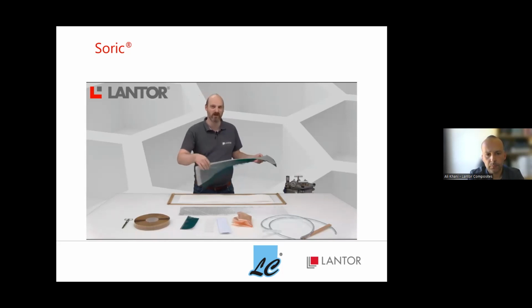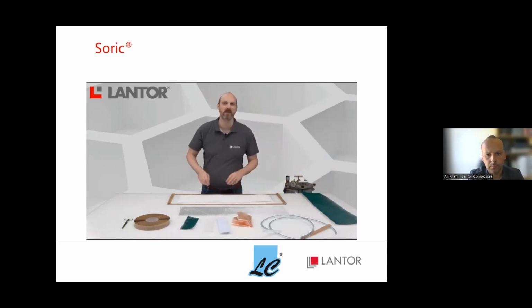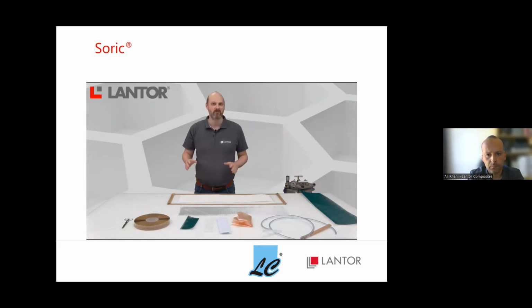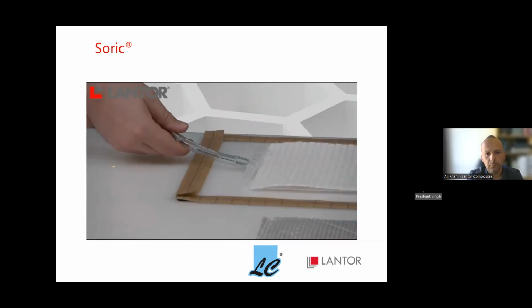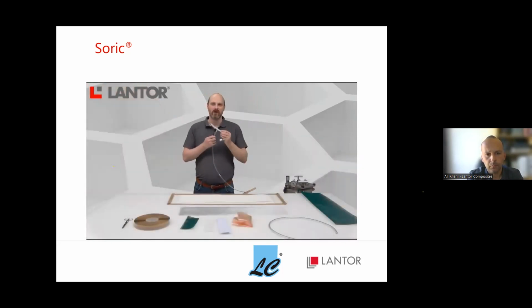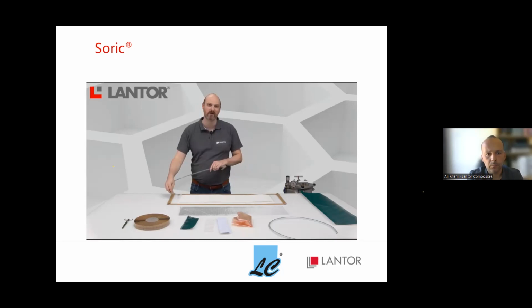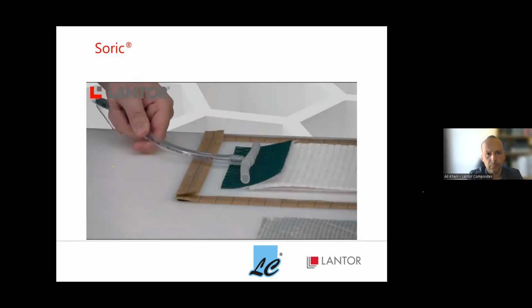We will not be using these large pieces, which will become waste, because it will be the Soric that is going to facilitate the resin flow. And unlike the flow mesh, Soric is part of the final product. That means that our resin feed line comes here. We stretch out the spiral hose so it stays open. And we position the spiral hose to make contact with the Soric to assure an optimal resin flow, aided by a small piece of peel ply and flow mesh where necessary.